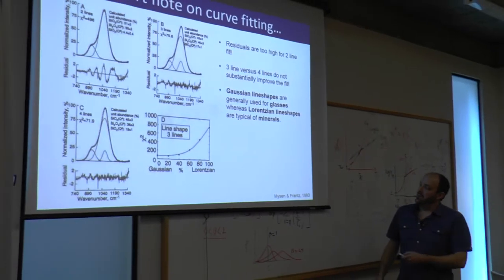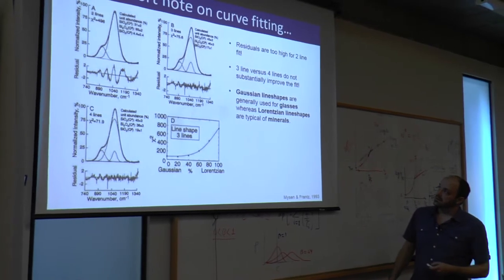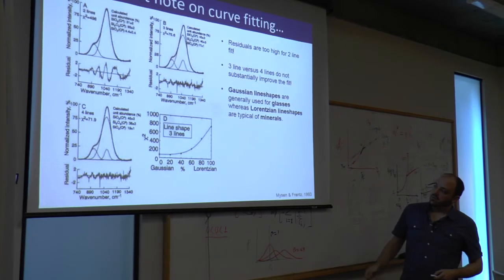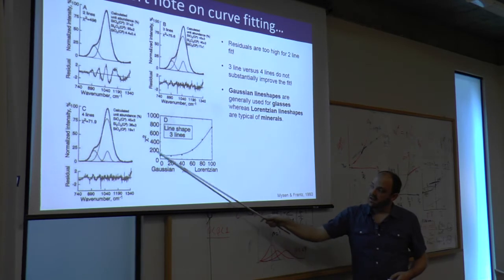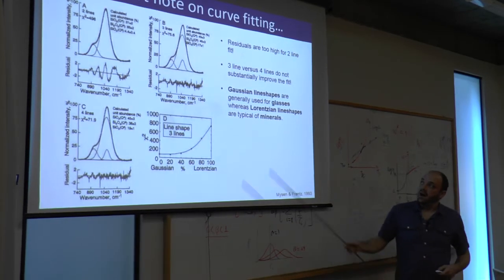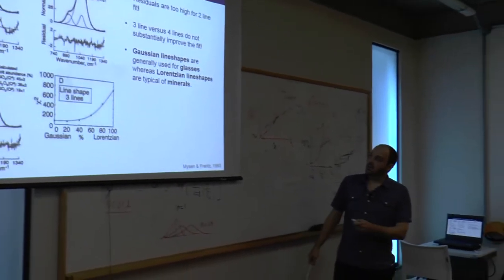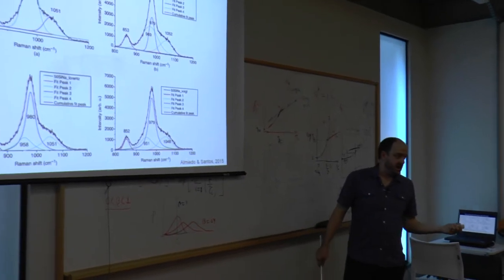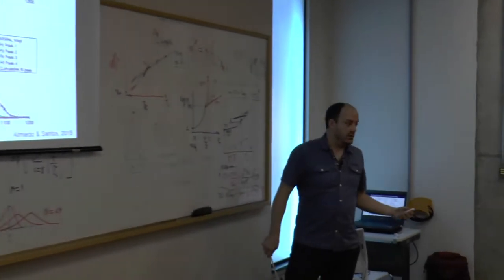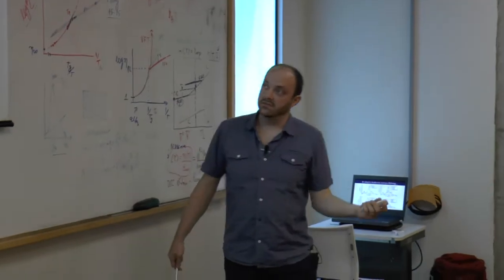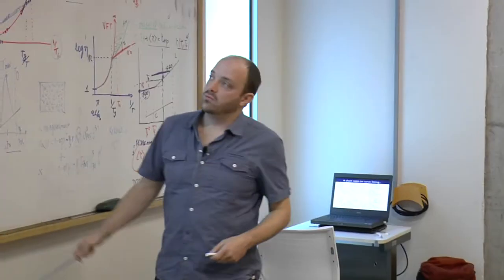And I'll go through my bottom lines for curve fitting in the middle. But basically for glasses, the main point is that we use Gaussian line shapes, and you should try to use as few lines as possible unless you have a justification for why you're putting bands in a given spot. Just a few more examples.